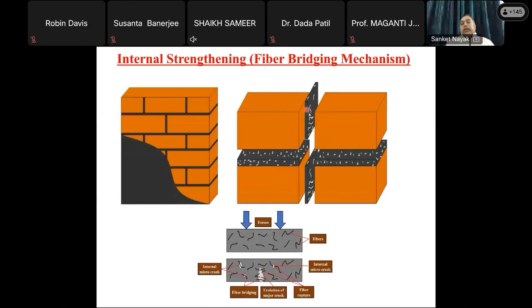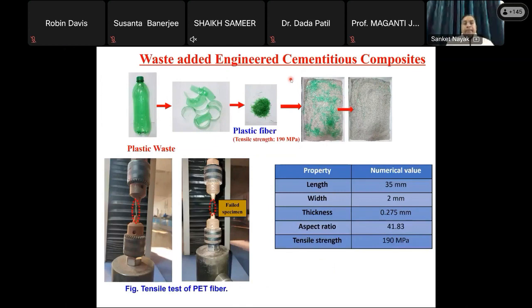In this case, you can see the reinforced mortar is provided between the two bricks and between the two brick layers also. So this is the mechanism which is effective to contribute to fiber bridging. I have shown you in one case how we are getting this waste plastic fiber from the plastic bottle. This is known as the soft drink bottle. So this is the dry mixing of the plastic fiber in the mortar. And why is it so effective? Because the tensile strength is very good. You can see about 190 MPa.